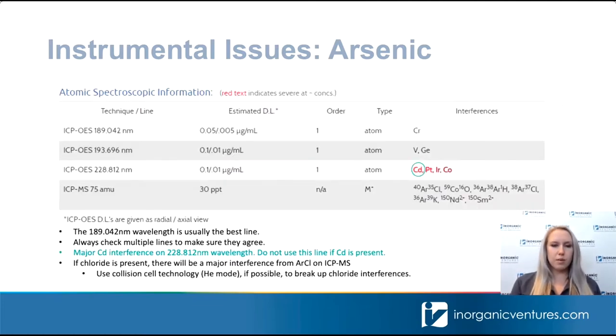This is a table taken from our website that shows the recommended lines for ICP-OES and ICP-MS for arsenic that we use here at IV. Our most recommended line on OES is the 189 wavelength. There is a chromium interference on this line, so make sure that you are looking at multiple lines each time you do an analysis to ensure that they agree and you're not seeing an interference.